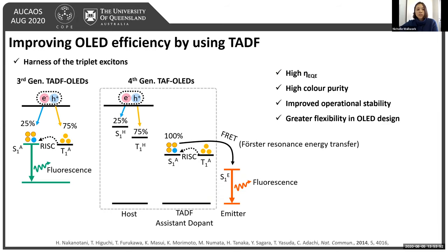There are two ways that literature utilizes TADF to harness triplet excitons: in third-generation TADF OLEDs, and in fourth-generation TADF-assisted fluorescent OLEDs. In TADF-assisted fluorescent OLEDs, TADF is used as an assistant dopant to upconvert 100% of the excitons formed within the host, which are then transferred to the TADF, and subsequently 100% of excitons are transferred to the fluorescent end emitter via Förster resonance energy transfer (FRET) to emit with 100% IQE from the end emitter, generally increasing maximum EQEs achievable to around 25% and resulting in higher color purity compared to regular TADFs due to a narrower emission spectrum.